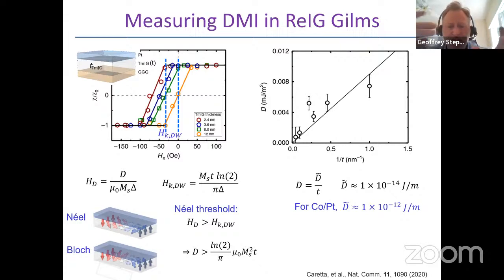You can essentially think of a domain wall itself as a rectangular prism. And that rectangular prism has a shape anisotropy. And so the shape anisotropy of a domain wall under these conditions would want it to be Bloch. And if you have DMI, it can compensate that shape anisotropy to force it to be Néel. So the amount of DMI that's required to make it Néel depends on the shape anisotropy energy that goes as MS squared.